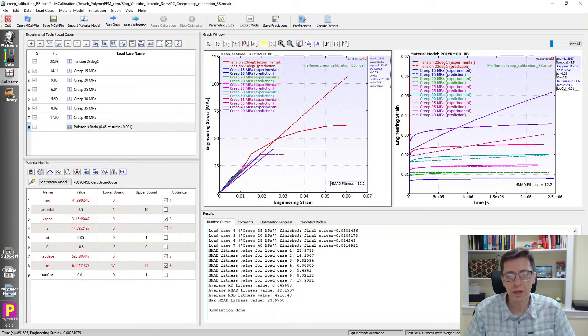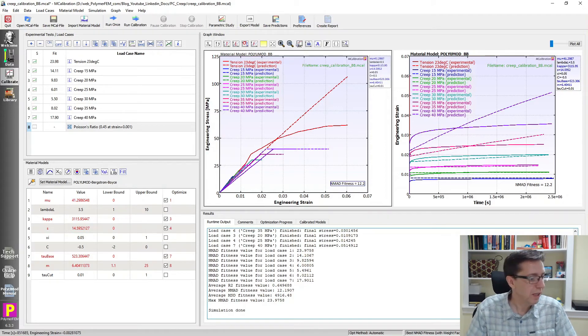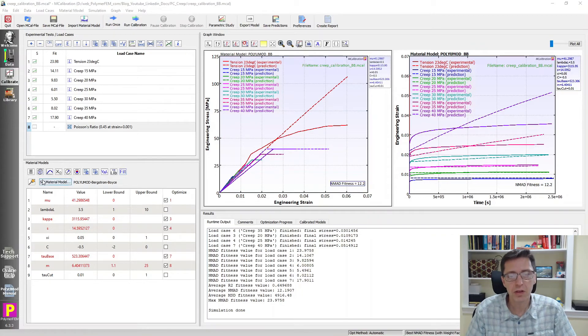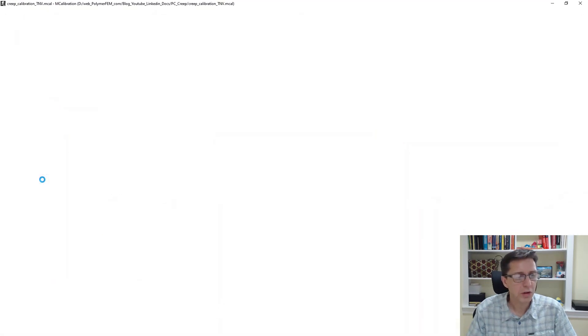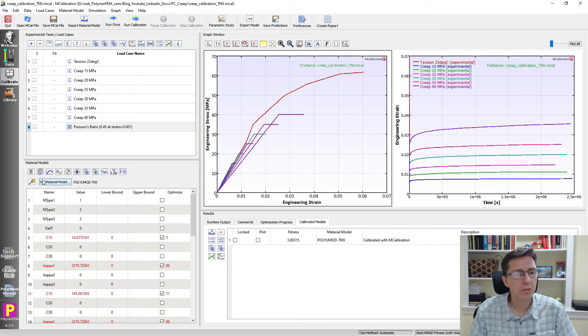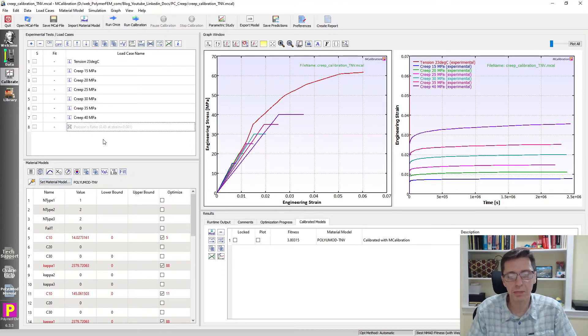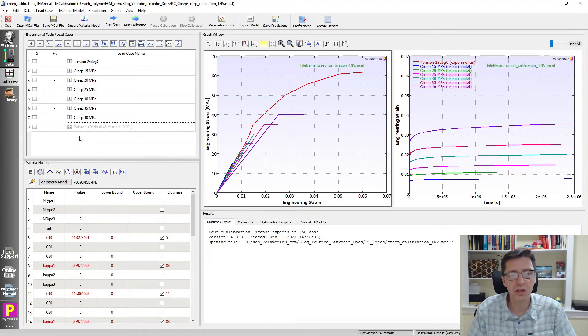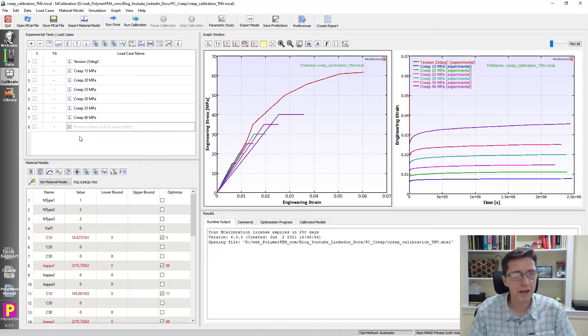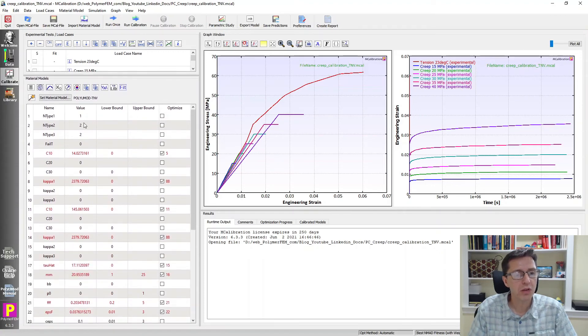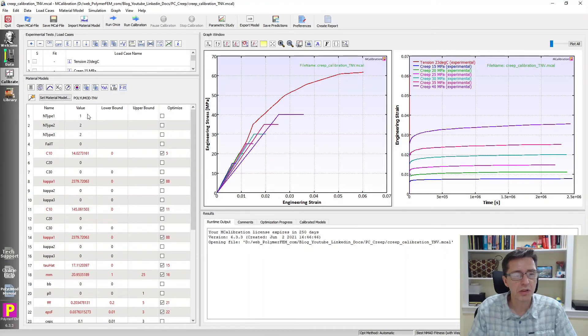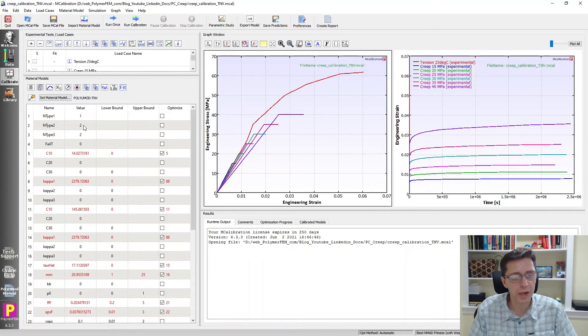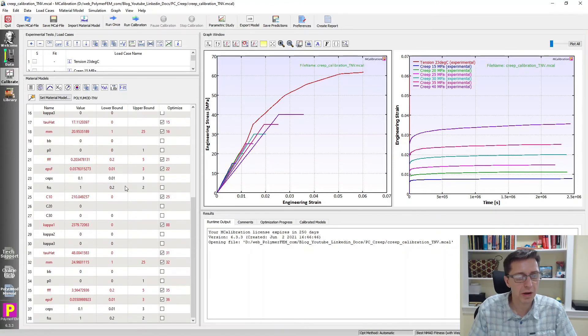So what is the model that really works then? I have a good model here that I'm going to show you. This is a material model that I call the TNV model. This is my current favorite material model. The TNV model is part of the PolyUMod library. TNV stands for three network viscoplastic model. I use this modular model with three networks here. You can see that this is a Yeoh hyperelastic model and two flow elements in parallel. I just calibrate this. I don't use all the fancy features available here. I use a yield evolution response in addition to power law stress behavior in the flow behavior.